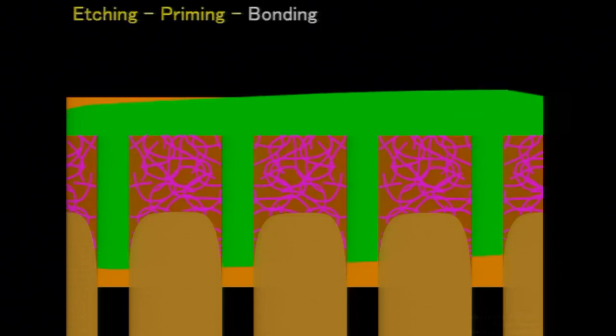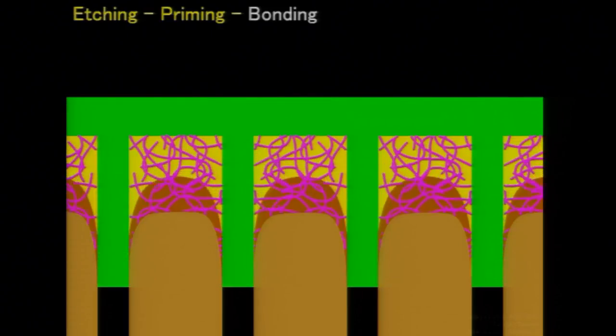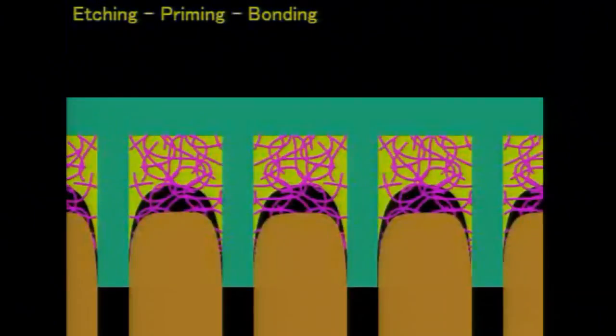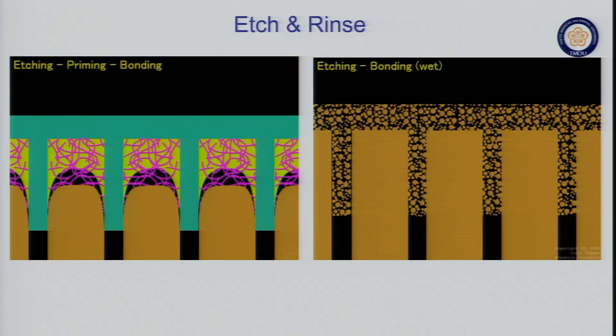However, the etching with phosphoric acid is too aggressive. It is too deep for the bonding resin to penetrate up to the bottom of the demineralized layer. That's why some dead space existed even after the polymerization.